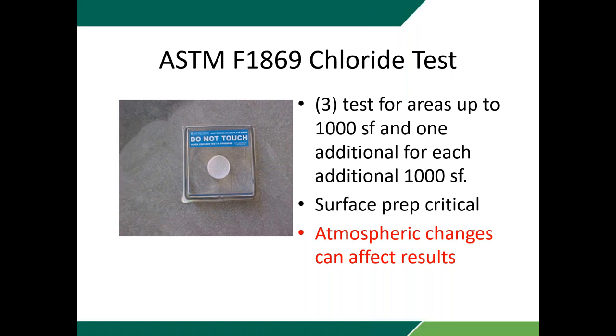And then after a given period of time, they come in and they pull that dome and they take that dish out with the chloride and they weigh it again. And the difference in weight tells them how much moisture that chloride has absorbed. And then they can calculate what the moisture drive is based off of that.